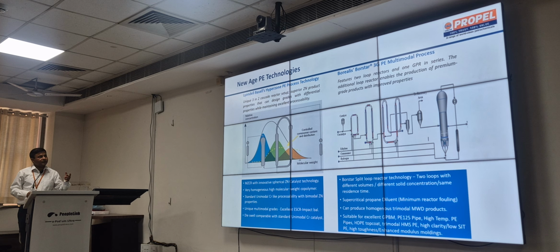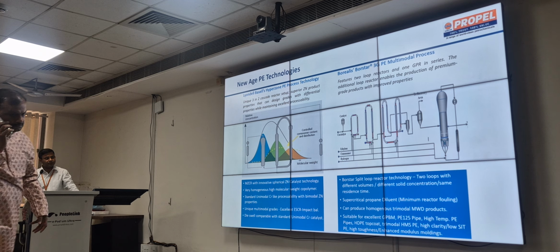Some of these multimodal advanced new age PE technologies is called Hyperzone. This is Hyperzone's 3x2 cascade reactor setup. Basically, it's called multi-zone circulating reactors, and the catalyst system where you can produce much superior high molecular weight. This technology can easily give consistency in terms of molecular weight distribution, and different sets of molecular weight distribution, narrow, broad, and much broader. So in the curve you can see the different molecular weight distribution products which are produced through this reactor system. And the Borstar third generation technology is based on a similar kind of, not the Hyperzone system, but different loop reactor system combinations where you can produce this.